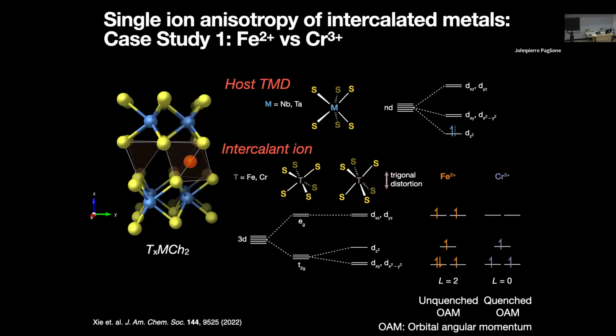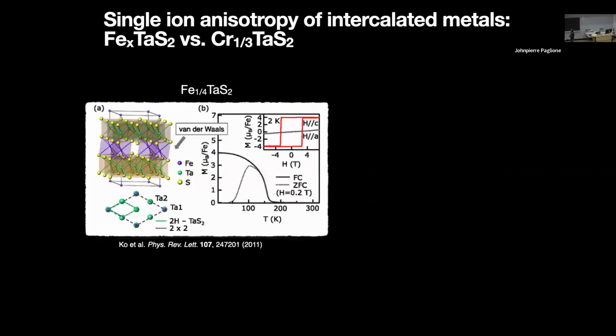It's not fully suppressed. But then for chromium, whereas for a free ion you would still have a non-zero L, now for chromium, which is d3, you've half filled the xy and the x squared minus y squared orbitals, and so you can't have electrons hopping between these two orbitals, and so then you have L equal to 0. Basically, you can say +2 and -2 cancel out, and so in this case you have quenched orbital angular momentum, and that's going to have a significant impact on the magnetic properties of the extended solid, and we'll look at just a couple of examples.